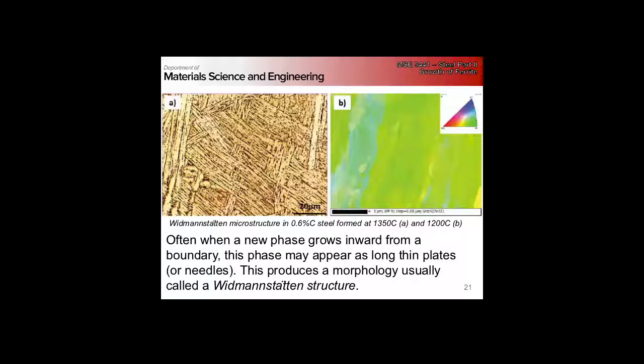And this is a Widmanstatten structure. And so here is an electron back scattered image, colored by the crystal orientation, and notice that within and in between the needles, they're generally a low angle boundary. There's not a big orientation difference between the Widmanstatten plates.